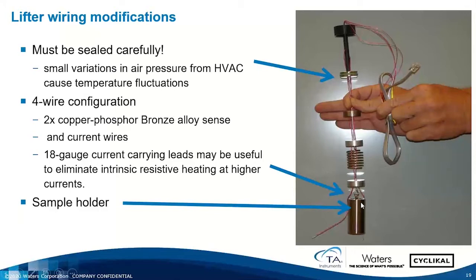The sample then is contained inside of the stainless steel ampule. Importantly, it's critical to seal this particular shunt from any influence that you might see from HVAC equipment. If there's any possibility of airflow through that thermal shunt, the stability of your thermal power signal will be very much compromised. So we use a 4-wire configuration to do our measurements, and this is critical for all the applications that we're going to talk about here. It has to be a 4-wire configuration.